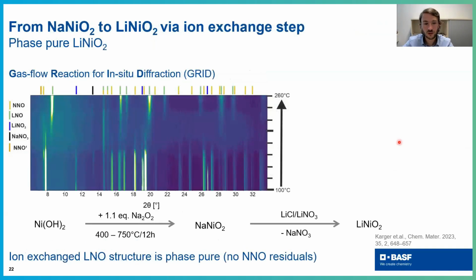So what was done here was ion exchange using a lithium nitrate melt, and this is also a very nice setup, a gas flow reaction cell for in situ diffraction developed also by Daniel Weber and Matteo Bianchini, which essentially allows you to monitor your diffraction patterns during the synthesis. So you have your capillary, and this capillary is in the XRD beam, and you are recording your diffraction patterns during the synthesis. In such a case, you start with sodium nickel oxide. These are these intense reflections here. And you have your lithium source, your lithium nitrate salt. And then you're just heating up your capillary.